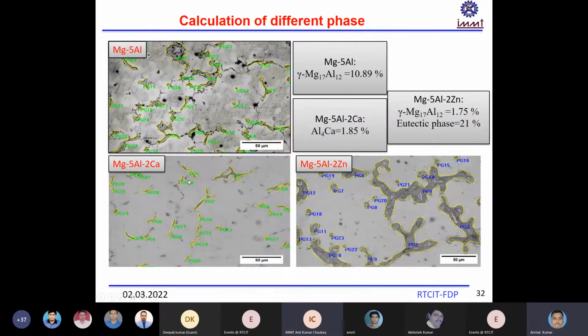But in the calcium alloy, the gamma phase was completely eliminated, though this Al4Ca phase is around 2% in this case. And in the case of zinc, the gamma phase is around 1.75%, but another eutectic phase, the magnesium, aluminum, and zinc phase, is much more, around 21%, forming in this case.